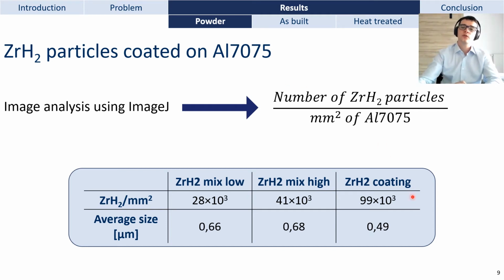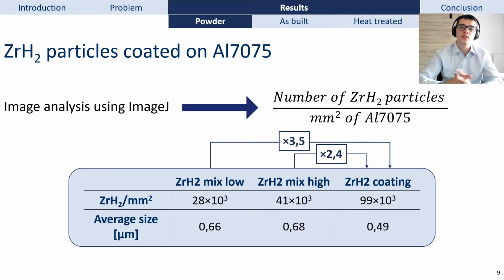If we compute the size of these small particles, we can see that it is below 1 micron for the three different powder mixes. What is really interesting to notice is that the plasma-coated powder exhibits much more zirconium particles on its surface than the low content mix and the high content mix. So once again, the quality of the powder is better for the plasma coated one, even though the zirconium hydride's initial powder was not sieved.